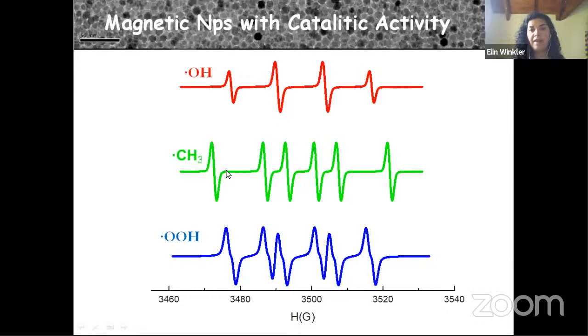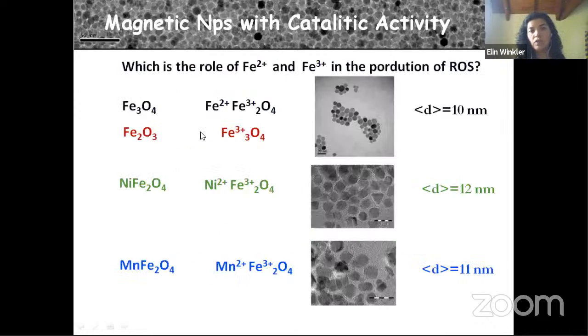Each particular radical has a very different signal that is like a fingerprint of which radical we are talking about. The double integral of this signal is proportional to the concentration of the radical. So we measure different systems, because in this case we want to observe the role of iron 2+ and iron 3+ in the production of the free radicals.